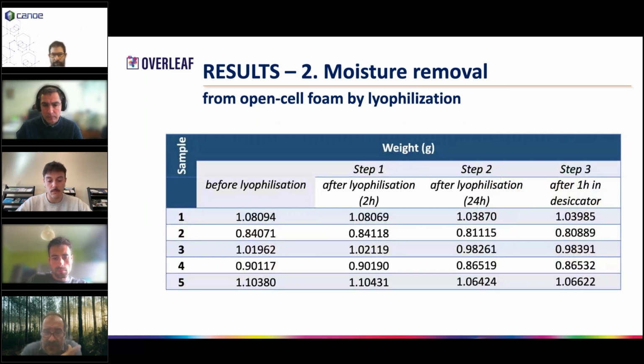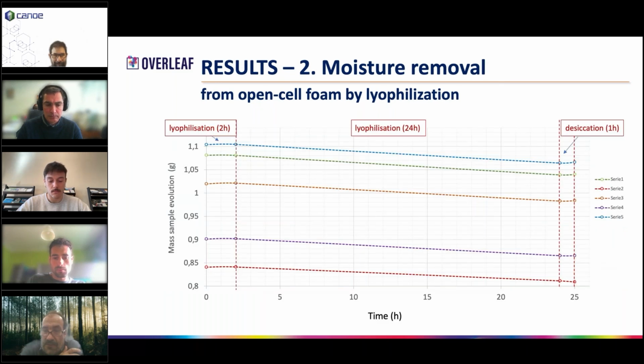As real values for this, you can see that we recorded after 2 hours, after 24 hours, and the third step is after 1 hour back in the desiccator. Why did we do this? Because the results are very interesting. Lyophilization is a process with better efficiency of water extraction. After we kept our samples in the lyophilizator and put them back into the desiccator, actually the samples extracted humidity from the desiccator itself. It was a very interesting phenomenon, and this gives us an idea that the lyophilization process is faster and more